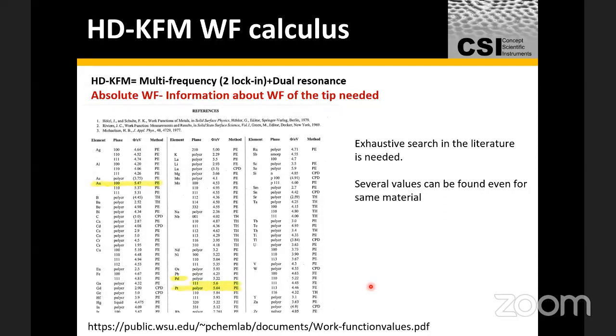So I guess it's fair to say that when you're measuring work function of materials, you're often talking relative rather than absolute terms. Although the absolute measurements are pretty close to what you would expect, it's important to remember a lot of these lookup tables are translated from the bulk properties of the materials and not really platinum on the very fine tip of material that's only a few nanometers thick.